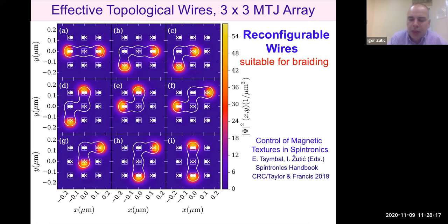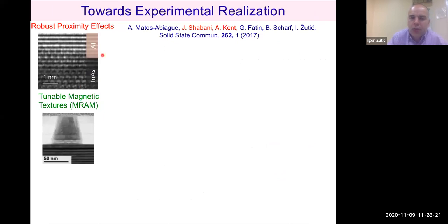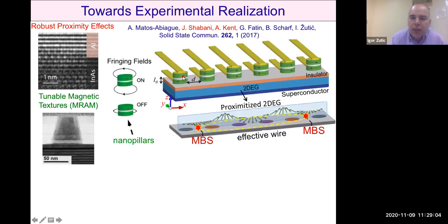However, this was a theoretical proposal, and some of these magnetic structures are not that easy to realize. So we teamed up with our experimental collaborators to see what is experimentally feasible, and maybe we can use these ideas in a slightly different platform. Our experimental expert in growing superconducting structures, Javad Shabani, can make very, very nice and sharp junctions between semiconductor indium arsenide and superconductor aluminum. Our other collaborator, Andy Kent, who is an expert in magnetic nanostructures, actually has a small company working on so-called spin transfer torque, where these magnetic nanopillars can be nicely made, and one can change even the direction of magnetization simply by passing current in these magnetic nanopillars.